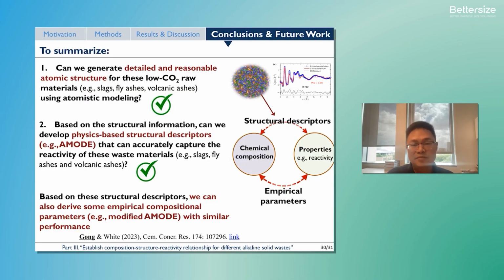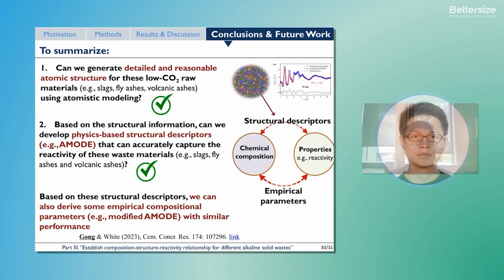So based on these results, we later extended this to develop a modified Amode parameter that can perform as well as the original Amode, but can be directly estimated using chemical composition without computationally expensive atomic simulation. So this can potentially be developed into a fast screening method for these waste materials for industry application.